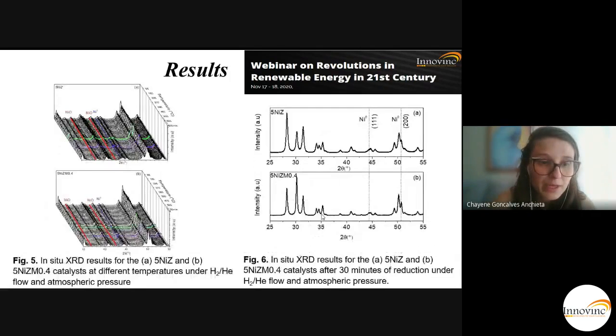Here, when we compare the reduction profile by using in situ X-ray diffraction, we can see that we have different profiles, and we also could estimate the average crystallite size using these results. And we can see that we have different profiles when we're talking about nickel zirconia with and without ionic liquid. The figure on the top left is the catalysts without ionic liquid in the support synthesis, and the figure on the bottom is the catalysts synthesized using ionic liquid. And we can see that we have differences related to the temperature at which the reduction starts, as we could see in the TPR profiles too.